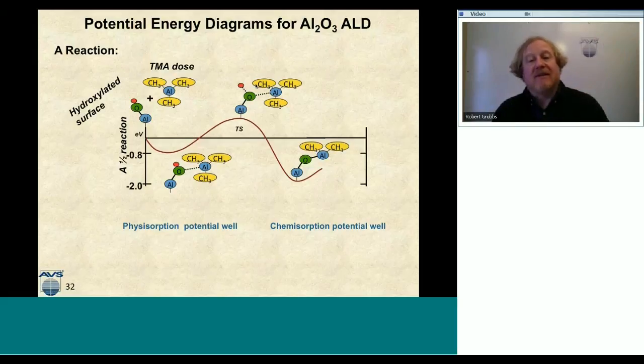And so as this happens, I fall downhill to the more thermodynamically stable bond, which is the aluminum-oxygen bond, and then my H is probably formed as H2 and leaves as a byproduct. Here I've fallen down into the chemisorption well. So I went from the physisorption well up through the transition state and then down into the chemisorption well to put my ALD precursor, my trimethyl aluminum, onto my hydroxylated surface. This is the A reaction.